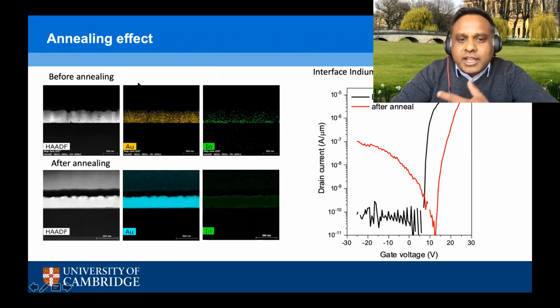So we've been studying how the alloying affects the device characteristics, and this is a cross-sectional TEM image with EDX mapping. One can see that before annealing, there is a concentration of indium at the interface between the metal and the semiconductor. It's kind of hard to see. This is the gold map. After annealing, we can see that there's a uniform distribution of indium and gold throughout the contact region. And before anneal, we primarily get n-type behavior, but after anneal, we can get some hole current as well, because you have some diffusion of gold to the interface.